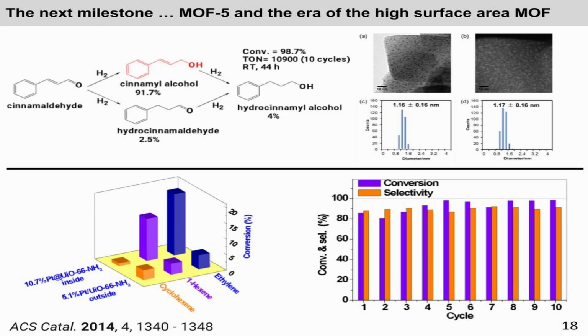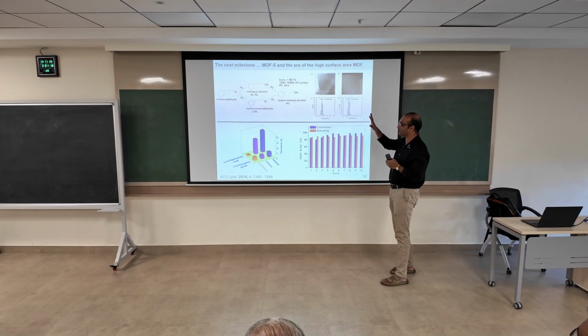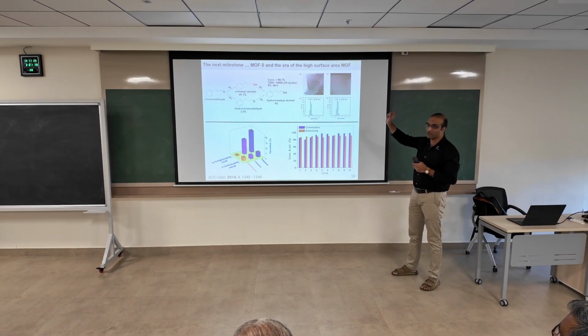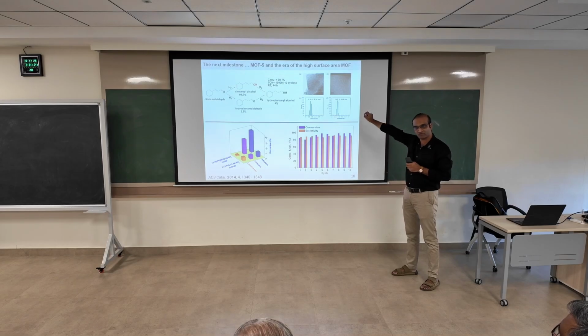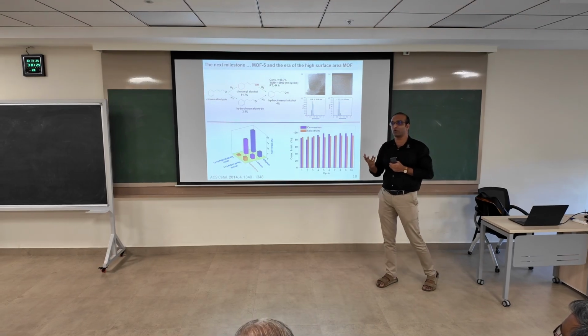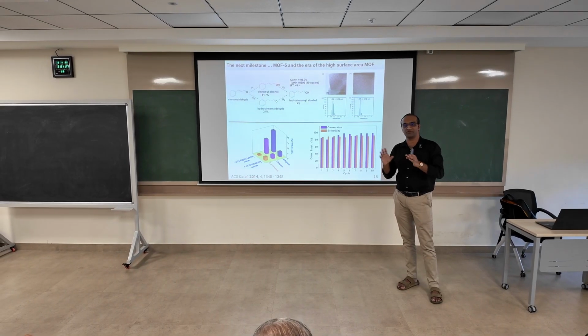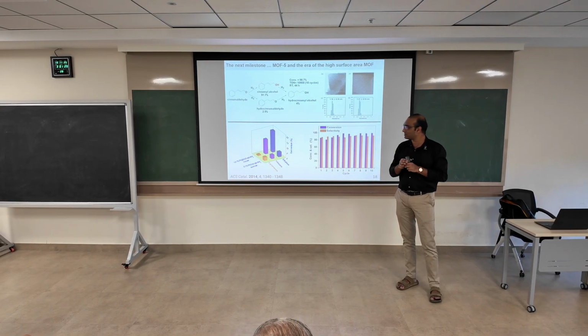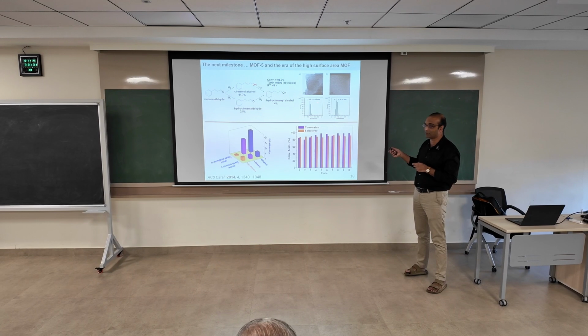In this particular work, what we did was we controlled the loading of the MOF. We first converted to getting this UiO66NH2 linker. Then we bound it with zirconium chloride, and we made the MOF. And the platinum was exclusively inside the MOF. First we load it as K2PtCl4. We take the platinum precursor, we load it into the MOF, and then we reduce it under hydrogen. And when it reduces, we can control the size to about 1 nanometer.